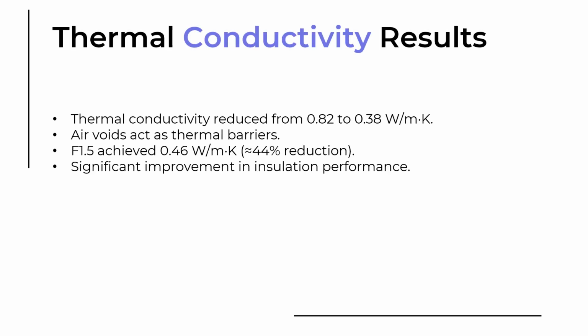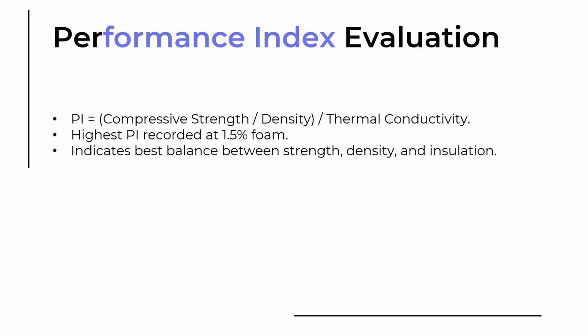For the thermal conductivity, it was reduced from 0.82 to 0.38. This is due to the air voids acting as thermal barriers, and we found that the optimal value is 1.5% foam with a reduction of around 44%. And we found also a significant improvement in insulation performance. For the performance index, the highest performance index was recorded at 1.5% of foam, and this indicates the best balance between strength, density, and insulation.